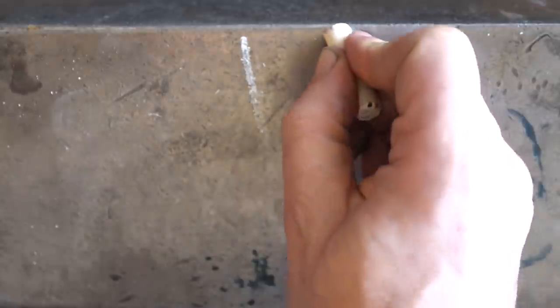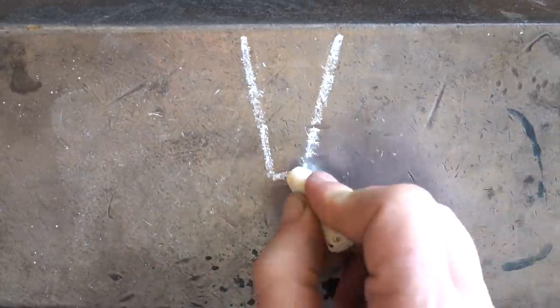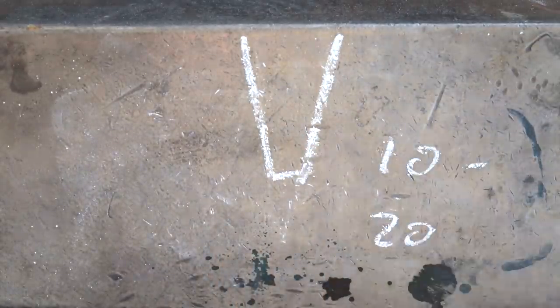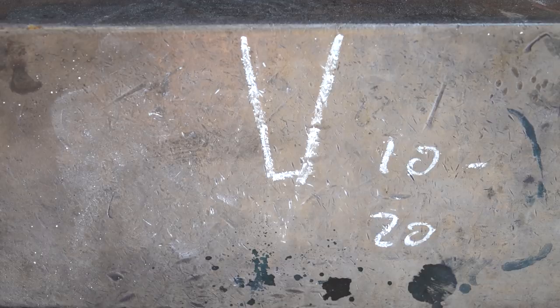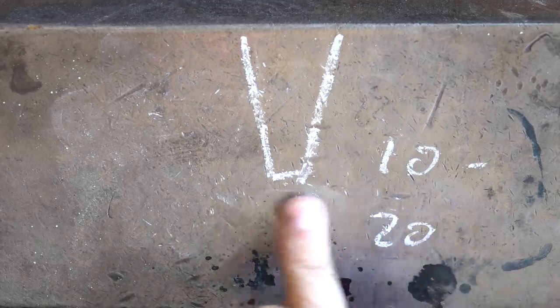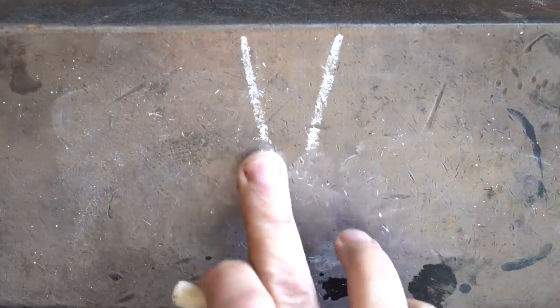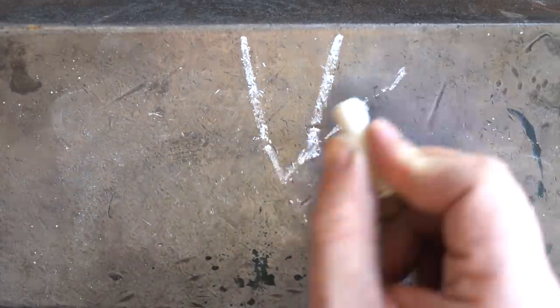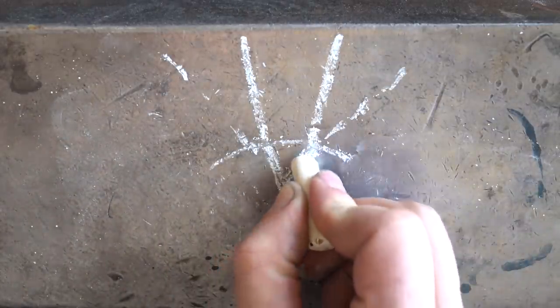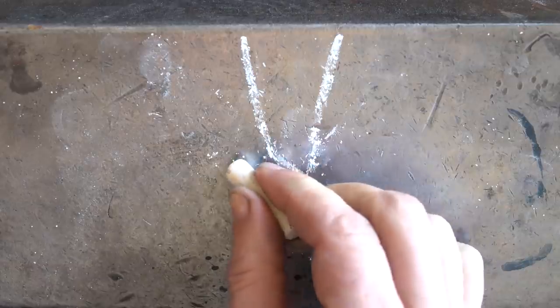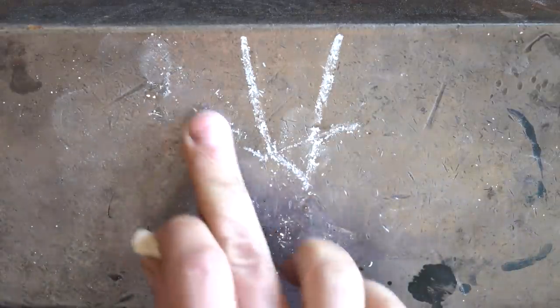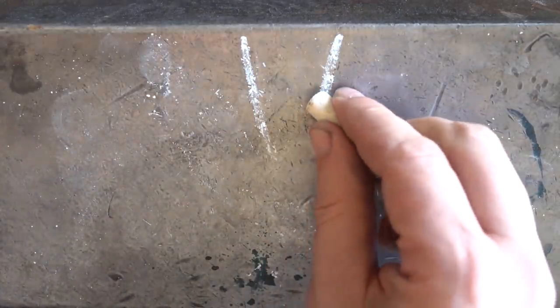Okay, after you finish grinding, you're left with something like this. You haven't sharpened it, but it's ground down very thin. For a chef knife, about 10 to 20 thousandths thick there at the very edge. And that is the edge to which you will apply your secondary bevel and form the cutting edge of the knife with. So you'll come in here and put in a secondary bevel, something like that, with a wider angle. There's other grinds. You can do chisel grinds. In the chef world, there's other more complicated grinds for Japanese knives, for example. But this is the idea. You have a slightly wider angle.